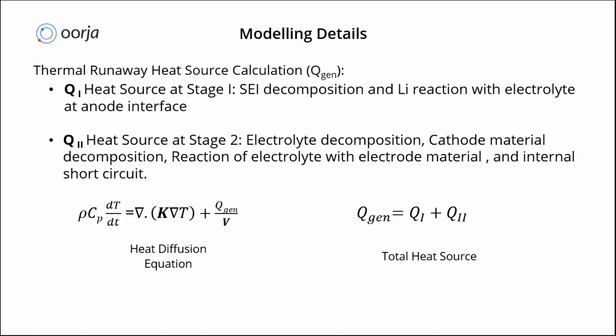It could be like the heat source at stage 1, wherein the SEI decomposition as well as the lithium reactions with electrolyte at the anode interface may happen. Whereas in the stage 2 reactions, there could be multiple other reactions like electrolyte decomposition, cathode material decomposition, and so on and so forth. So essentially, at these different stages, exothermic reactions will start happening. First of all, the stage 1 reactions will start, because of which the self-heating of the cell will happen. After that, because of this self-heating, the cell will slowly reach the T2 temperature, which is the thermal runaway triggering temperature.